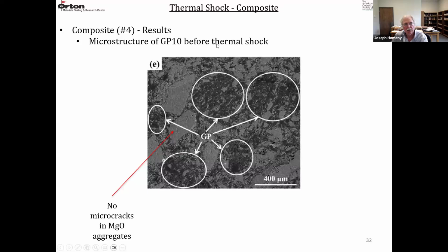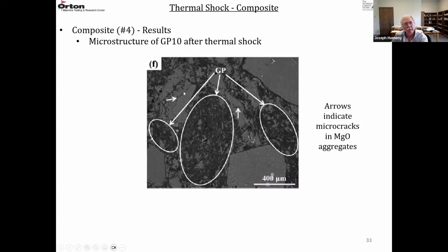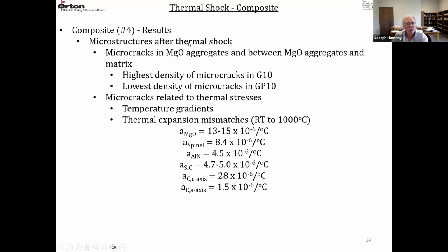This is a GP10 before thermal shock, and there's quite a few regions here where the pellets are located. And again, no microcracks in the MgO aggregates. And then after thermal shocking, there's a couple aggregates that have some cracking, but most of the microcracks are taking place in these areas where the pellets are located.